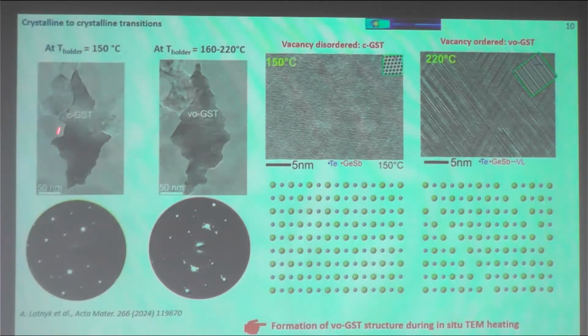If we heat up our cubic GST from 150 degrees C to 160, we observed the transformation from cubic to vacancy ordered phase. So this is the high resolution image. It shows the random distribution of vacancies in this cubic phase. And then at the temperature like 220 degrees C or 160, we can start to see such lines in this system. And this is a signature of the formation of vacancy layers. It can also be confirmed by selected area electron diffraction.